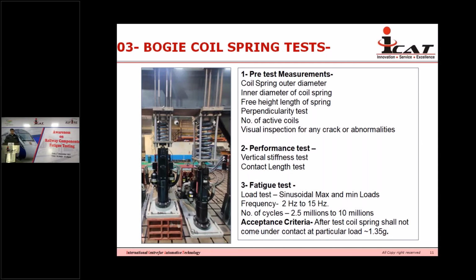And generally we keep the spring temperature up to 50 degrees, where there is no micro level change in the spring materials, or any kind of change in material behavior during the speed of the test. So we can conduct this number of cycles up to like 25 lakh cycles or 1 crore cycles. In railway, generally I have seen the number of cycles for any kind of fatigue testing up to like 25 lakh cycles minimum.